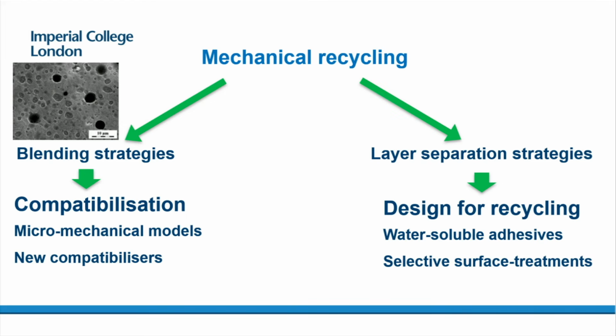What you can do is to add a small amount of chemicals, called a compatibilizer, which changes the adhesion of those two interfaces, and it therefore makes this material have much better mechanical properties. So we're performing studies here, both experimental and modeling, to understand the effect of compatibilization on the recycled material properties.